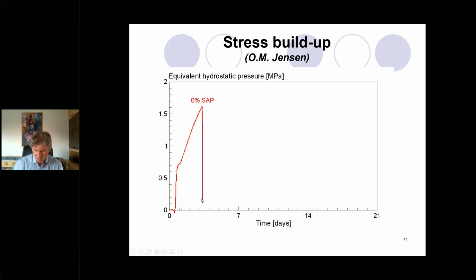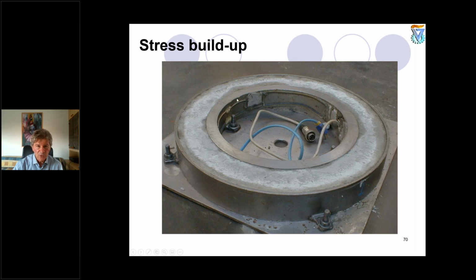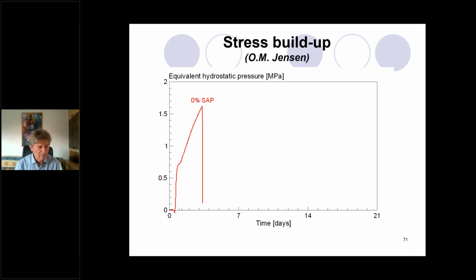How do we measure these stresses? By using strain gauges. You can see these strain gauges are installed on the internal surface of the steel ring. We measure the strains in the steel, and the modulus of elasticity of steel is well known, so we can easily calculate the stresses generated in the steel ring. And by some modeling, we can calculate, we can assume the stresses generated in the concrete itself, in this ring. This is called stress build-up in concrete. But again, this ring test is a standardized test. It's a part of an ASTM standard.